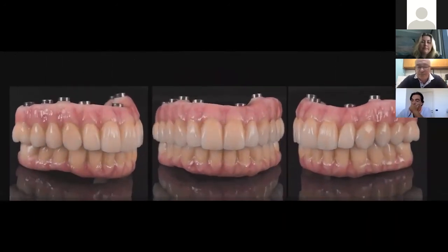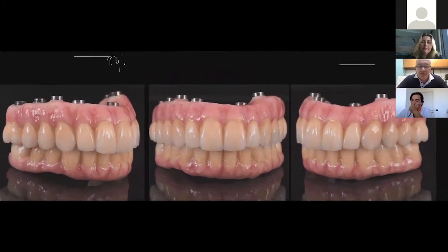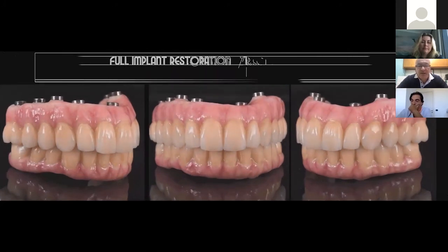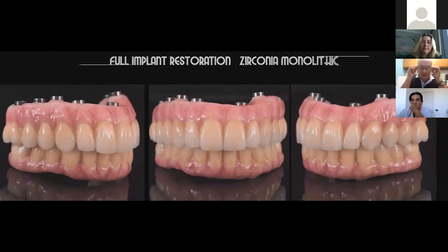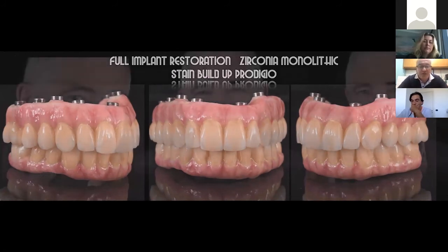This is a completely monolithic zirconia. We use only Prodigio stain. This case has been done with Dr. Mitrani, of Frank Spear Education in Mexico City. So we decided to use a completely monolithic restoration, to give as much translucency as we can. Actually it is an illusion of translucency, of course, including the pink of the monolithic. So no porcelain, really strong material. We are talking about the one for all. This is really strong material, but at the same time, we can play with those stains.